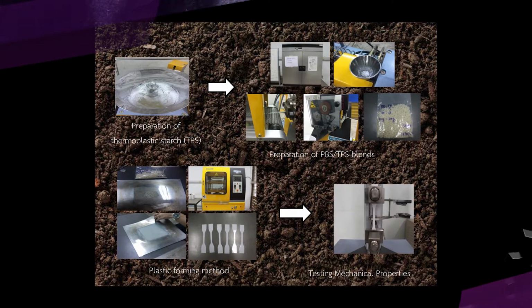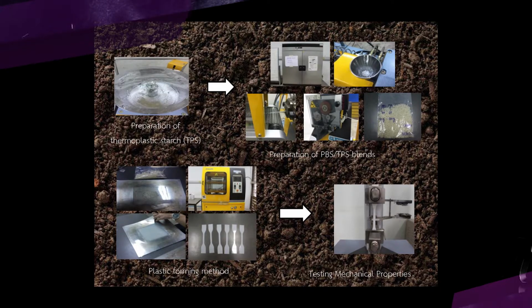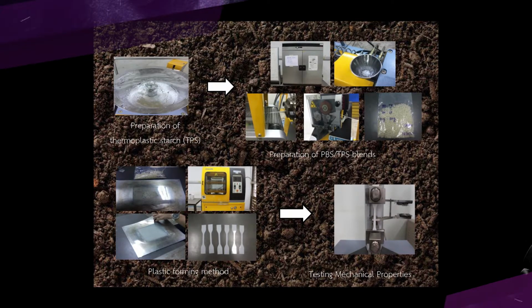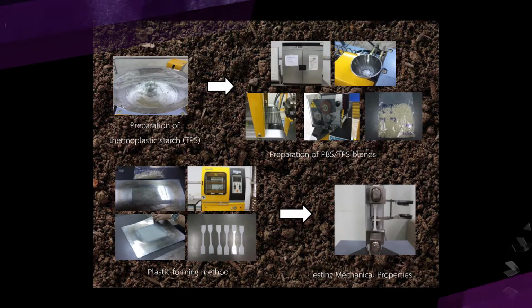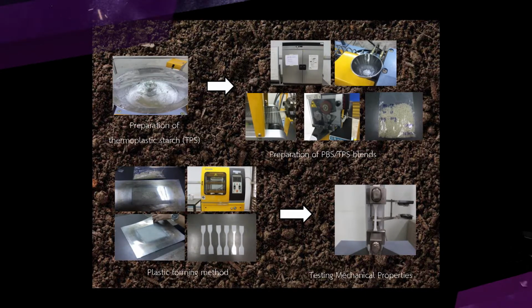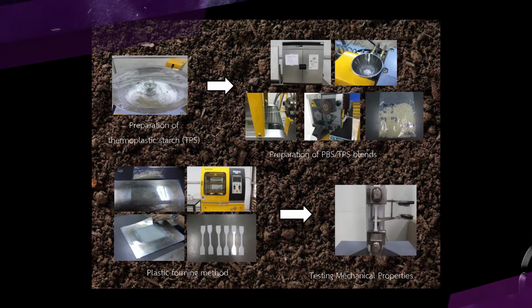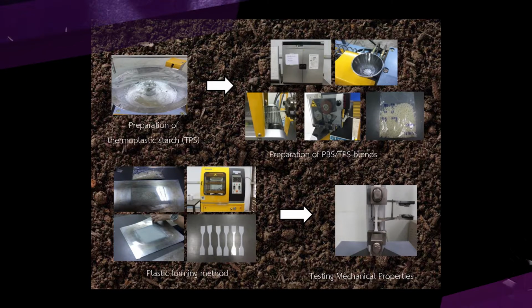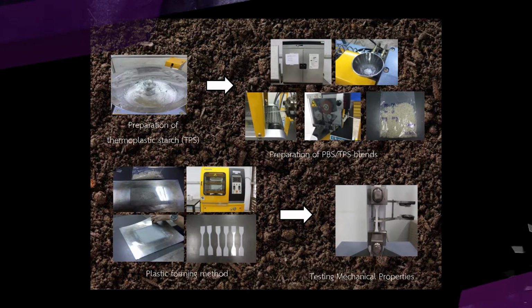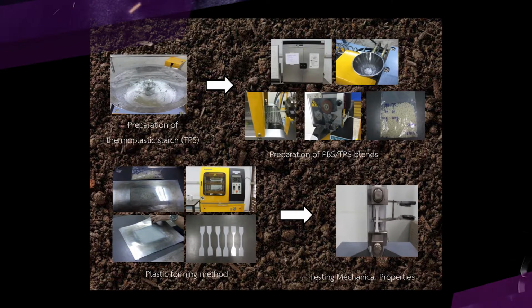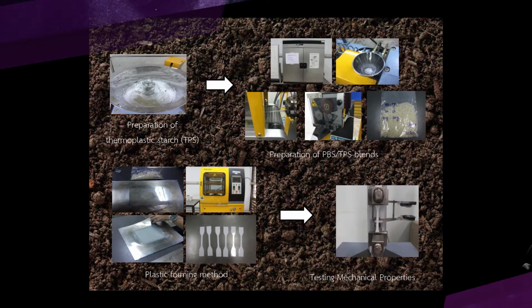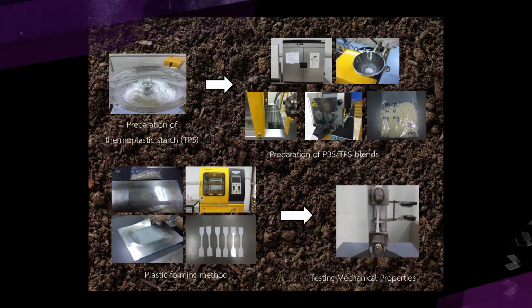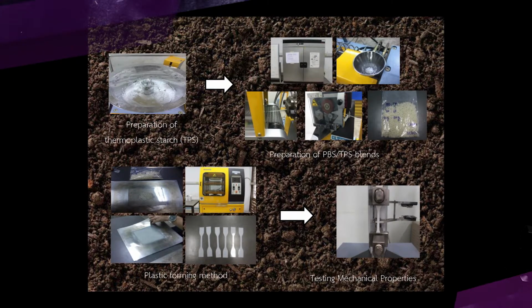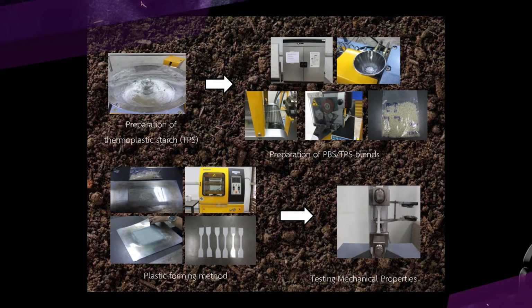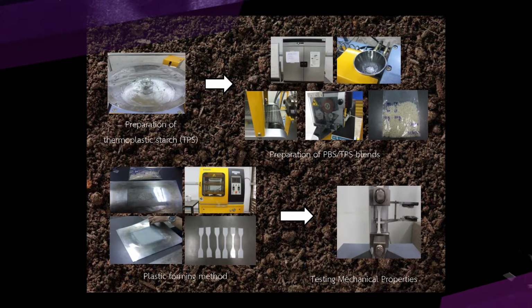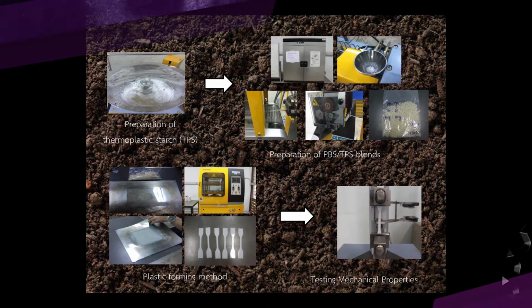the experiment by preparing thermoplastic starch by blending cassava starch with glycerol in a high-speed mixer for 10 minutes. Next is preparation of the PBS and TPS blend. We blend different ratios of PBS and TPS: 100/0, 80/20, 60/40, 40/60, 20/80, and 0/100. Then we blend PBS and TPS with a twin screw extruder and cut into cylindrical pellets.